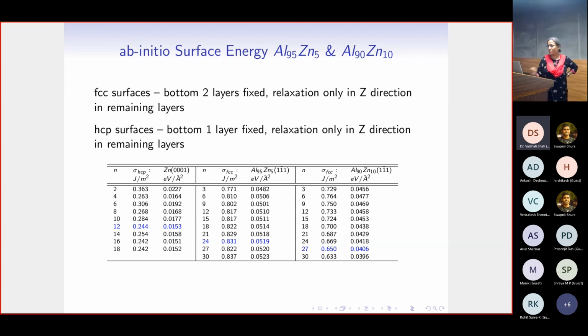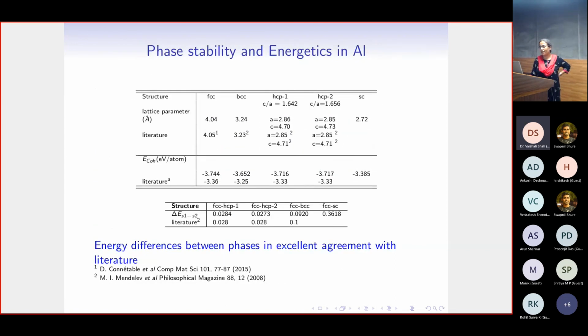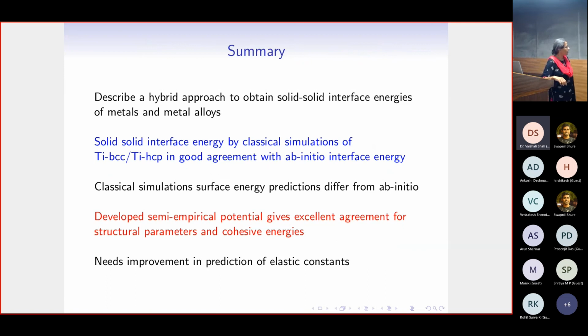Which is why I said it would be so nice if we can have, this was there in the summary I put in, no? If we were able to obtain the surface energy predictions reasonably well using classical simulations, then it would bring down the estimation time of interface energies by a considerable amount. All I need is a good potential that would be able to predict the surface energies more or less approximately accurately with what the ab initio gives. What we are saying now is that the interface energy is coming out correct because the differences it's able to predict correctly, but the individual surface energy numbers are not coming out correct.